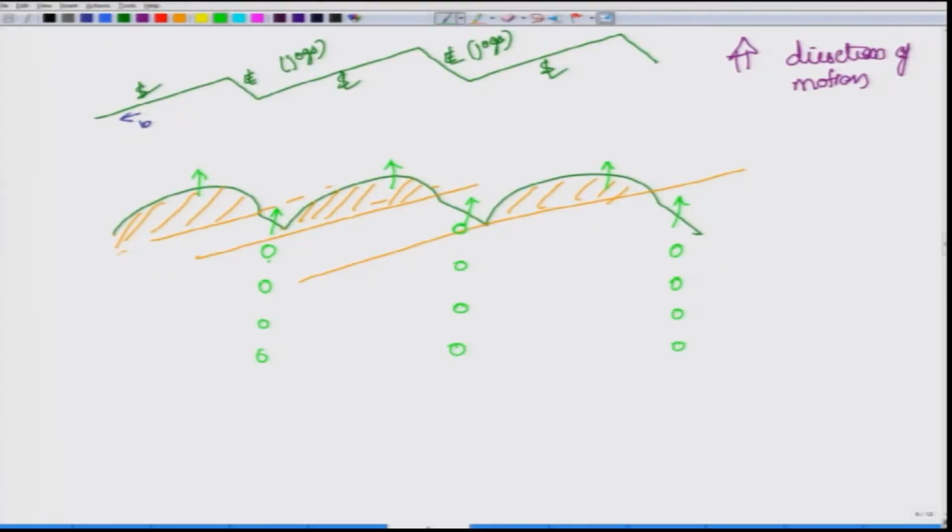So, this is the motion, and here you will have, let us say, we can describe a radius r. So, we can also say that the radius r which will be formed over here would be given by, if tau naught is the stress being applied, then the radius of these dislocations would be equal to alpha GB by tau naught.